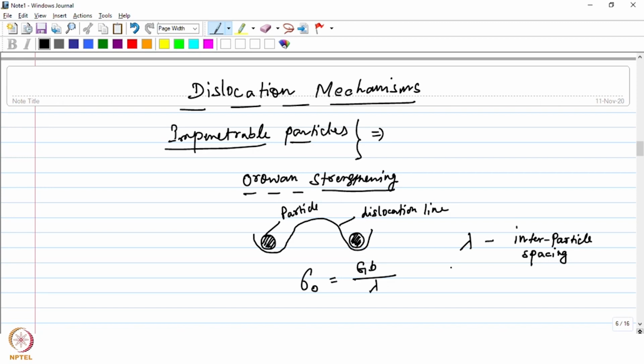And this is what happens when you change the particle size. When the particle size is finer, the distance between them will decrease, and as a result, a composite which is reinforced with finer particles will give rise to higher strength compared to a composite which is reinforced by coarser particles. So this is one of the dislocation mechanisms which can operate in a metal matrix composite, but there could be others also. So let us see the other dislocation mechanisms also.